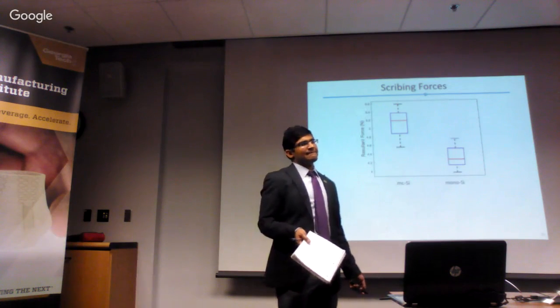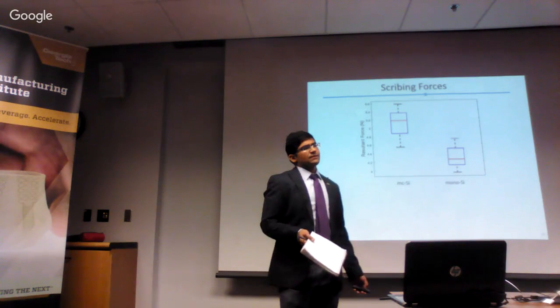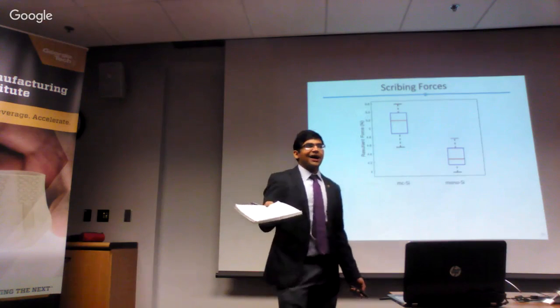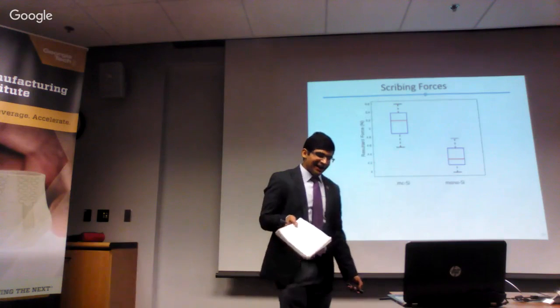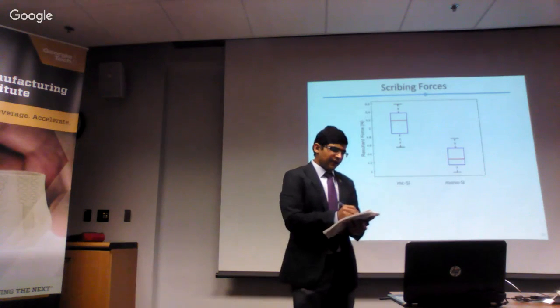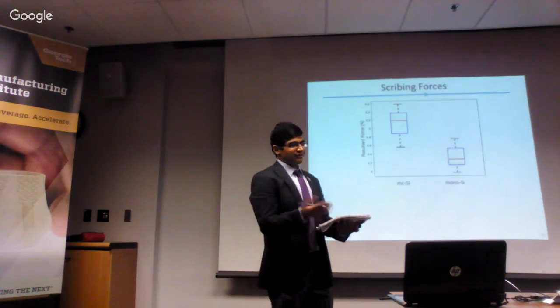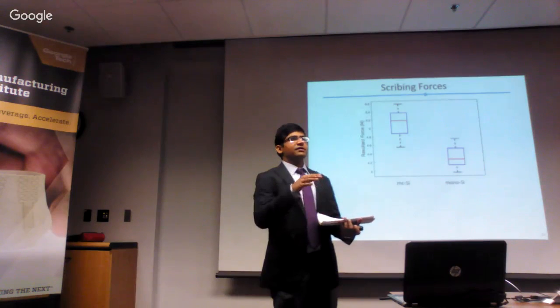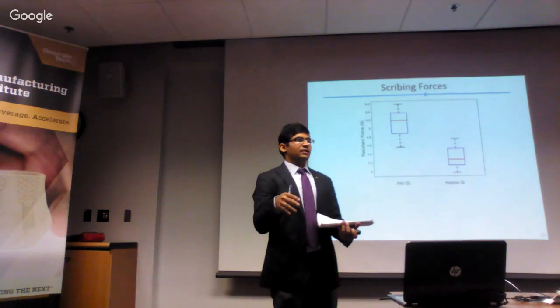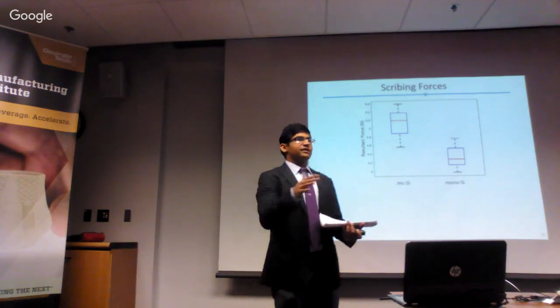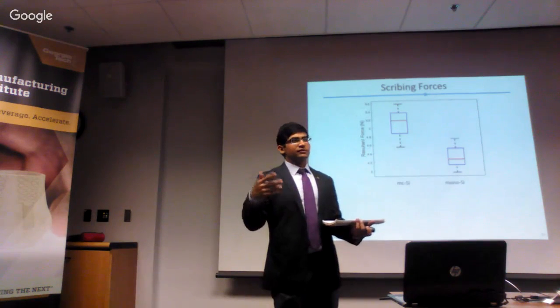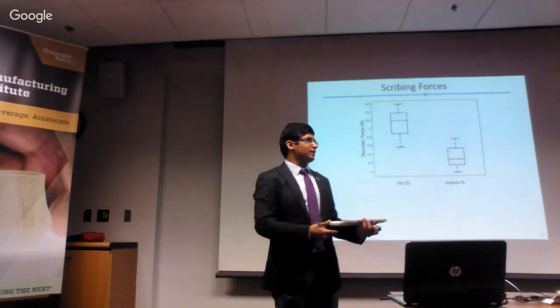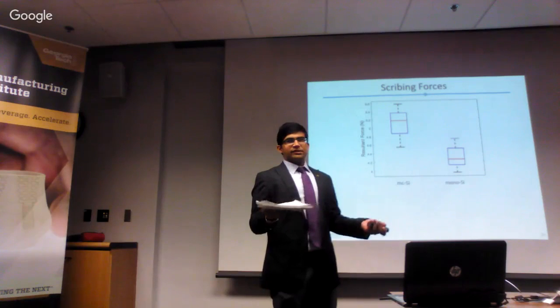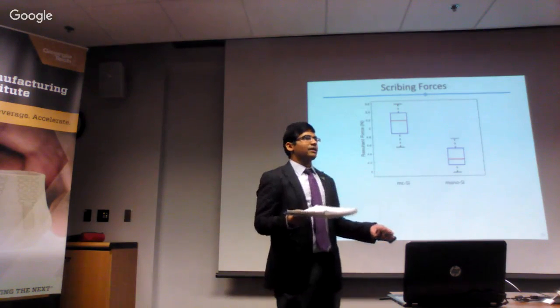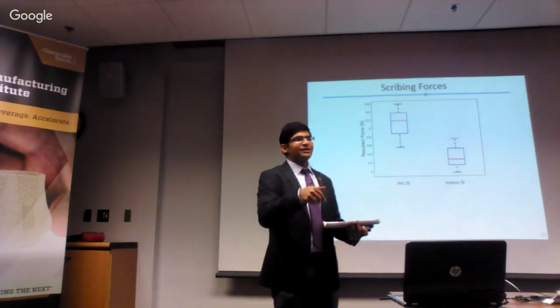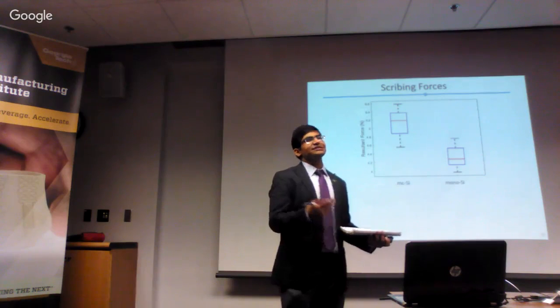Has anyone reported why the K1Cs are very different for these materials near grain boundaries? Is it because of dislocation pile-up on the boundaries? I think in your thesis you talked about just the interface being a natural discontinuity. I did some experiments way back in 2012 when I started, and they are not in the thesis. We found there is a K1C correlation with dislocation density. Dislocation density and K1C are interrelated, and K1C depends on dislocations. But in that study we only looked at dislocations; there could be other things at the boundary, like impurities or silicon carbide and nitride, which can affect the fracture toughness. When you are just doing an indent, we are not seeing what it is encountering. We're just seeing fracture toughness.